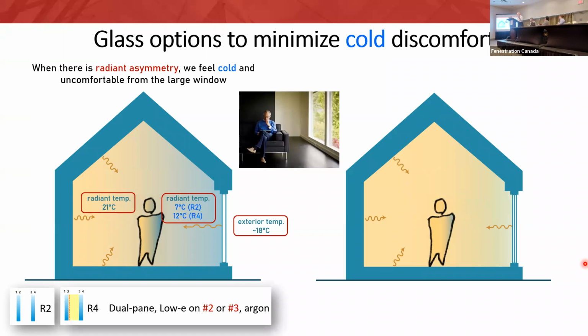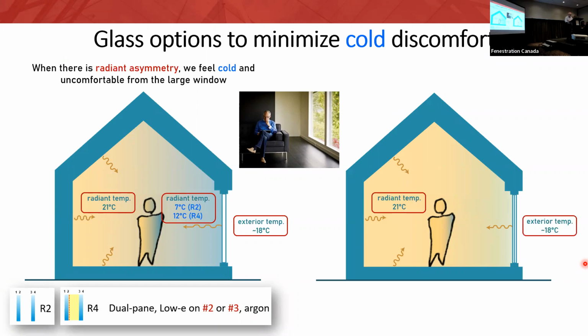If you improve that glass to what was the state of the art unit 20 years ago or more, it is a big improvement. We now have the glass surface temperature at 12 degrees. Big improvement if you were living with dual pane clear, and now you've got this, you'd be very happy. But you still have radiant asymmetry under these cold climate winter conditions.